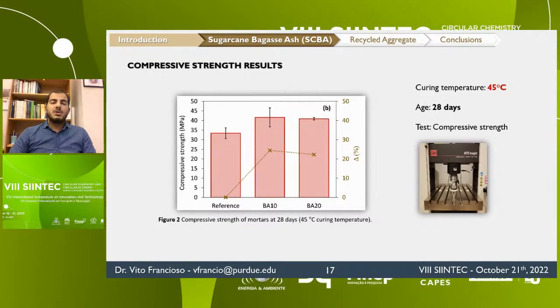However, when the samples were cured at a higher temperature, the mortars with sugarcane bagasse ash exhibited an increase in compressive strength, over 20% in both cases compared to the plain mortar cured at the same temperature. Thus, the results suggest that the curing temperature modifies the effect of sugarcane bagasse ash on the mortar's compressive strength.